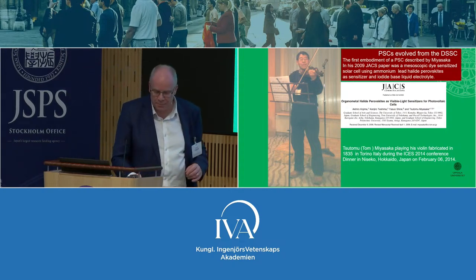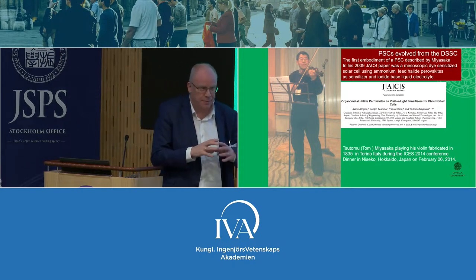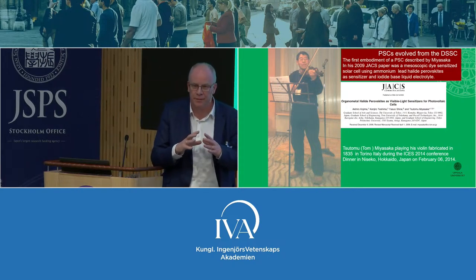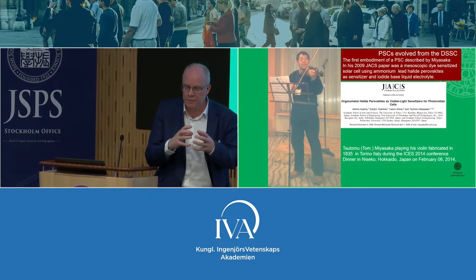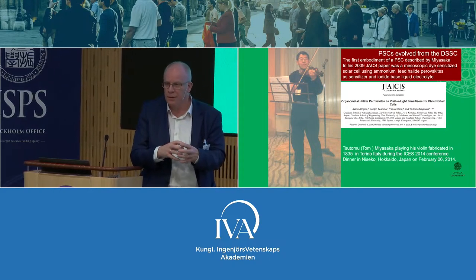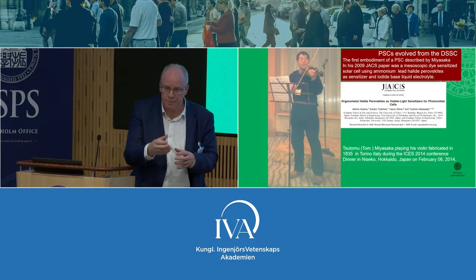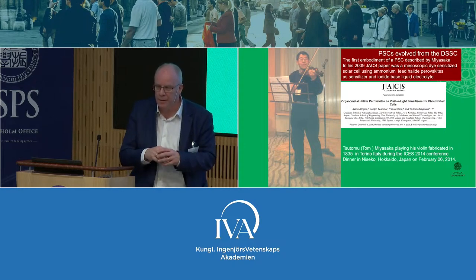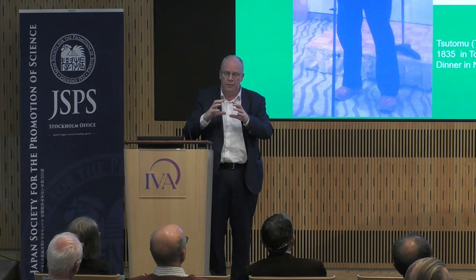What is also nice with the perovskite is that you also have a lot of chemistry to do. You have the A site, that's a cation, which started with methylammonium, but you can play around with that. You can have cesium, as you said, you can have formamidinium, you can work on the lead site and put in some tin instead, and you can work on the iodide side, which changes the energy levels, the band gap. So you can tune a lot of properties, and also the quality of the perovskite film is very important,